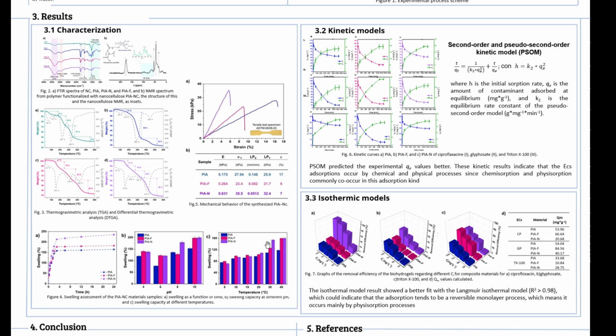showing intense oxygen-hydrogen stretching in the presence of nanocellulose, suggesting stronger hydrogen bond interactions between nanocellulose and polyitaconic acid, due to the deep eutectic solvents forming hydrogen bonds with natural polymers. Also, it can be appreciated that the polymerization occurred properly because of the intensification of the band characteristic of carbonyl groups. The carbon nuclear magnetic resonance analysis was used to observe the effect of adding nanocellulose to polyitaconic acid biohydrogels.